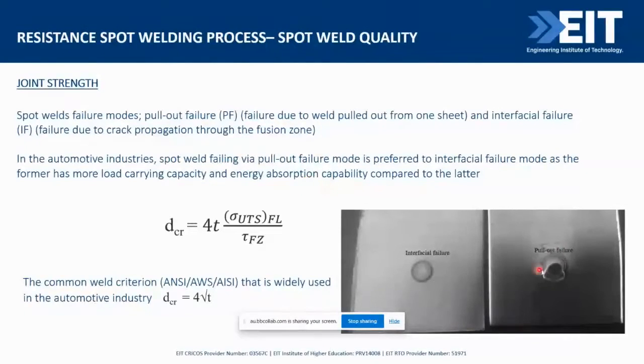Now, the pull-out failure is a type of failure where it was found that the weld is able to absorb a huge amount of energy before failure. So the spot weld is quite strong and is able to absorb a huge amount of energy before it fails, right? It's way stronger compared to an interfacial failure. Now, there are some standards, right?